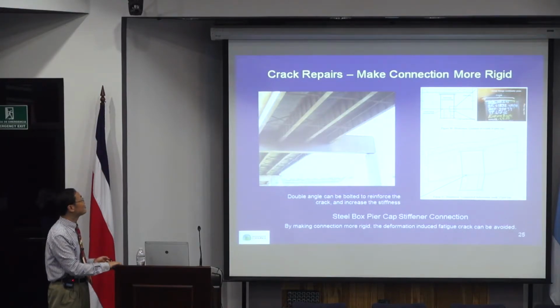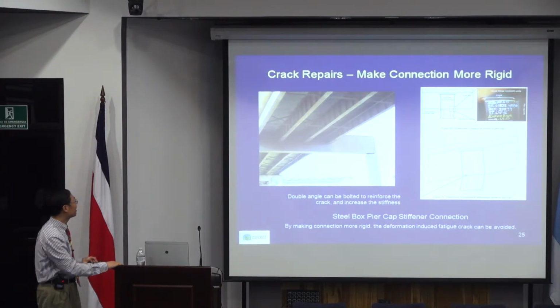And one of the particular details where we have experienced problems is the steel box connections. For typical piers, we have concrete and we will have a column there. Sometimes there's a highway underneath, so you cannot put a column there. So what people typically do is build a steel box pier, so that you have girders connecting to the box. And when they have load here, the diaphragm inside deforms quite a lot, and that causes fatigue cracks because of this uncontrolled deformation.